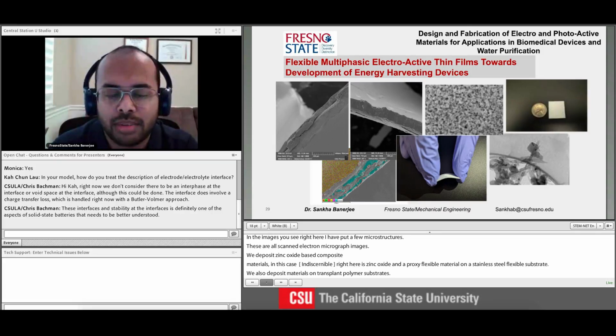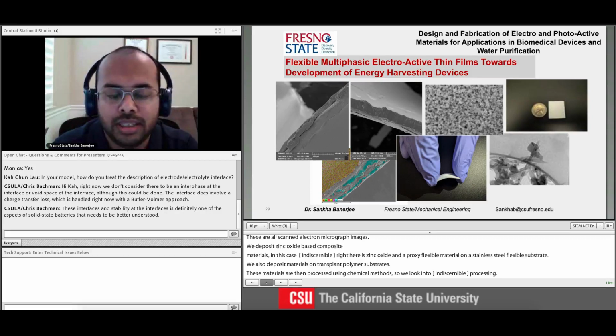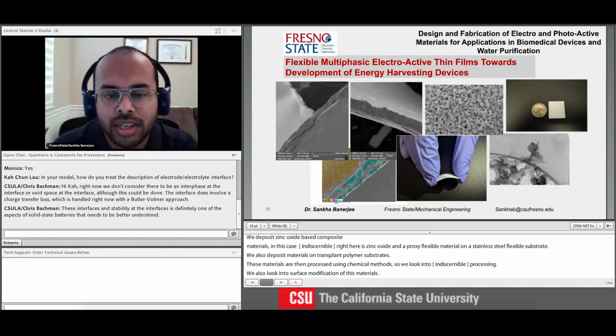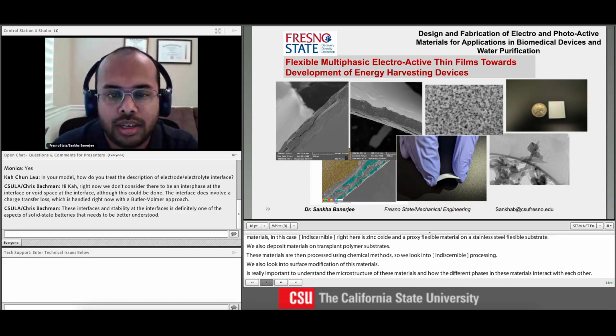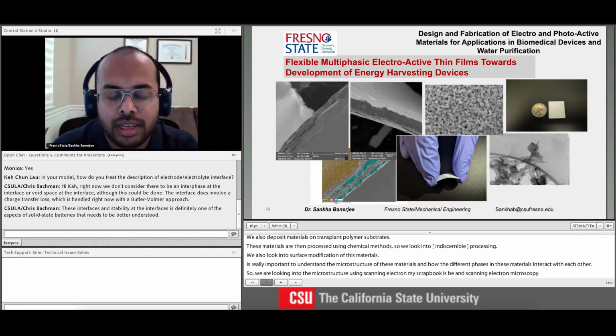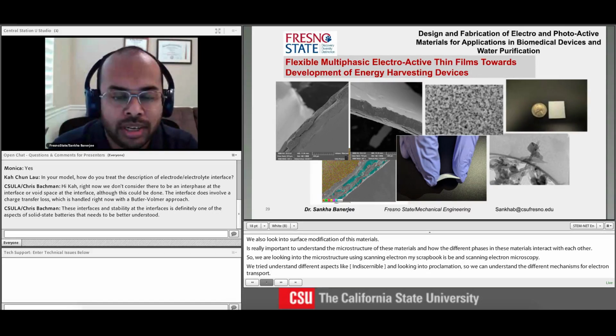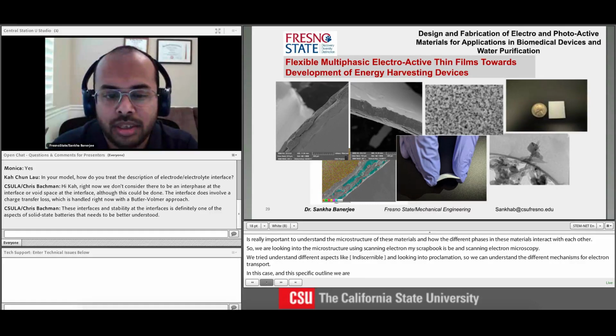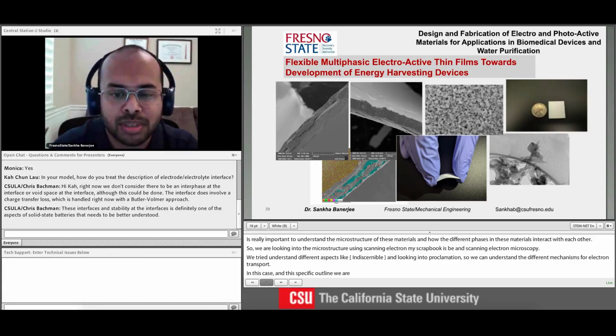Now, it is really important to understand the microstructure of these materials and how the different phases in these materials interact with each other. So we look into the microstructure using scanning electron microscopy and transmission electron microscopy, and we try to understand different aspects like agglomeration, also looking into percolation, so that we can understand the different mechanisms for electron transport. So in this specific example, we're looking at a zinc oxide epoxy composite, and we can also add a conductor material such as graphene or carbon nanotubes that is going to tailor the electron transport properties from the bottom of the thin film to the top of the thin film. And based on the tuning of these electron transport properties, we are able to get our desired performance for specific applications.